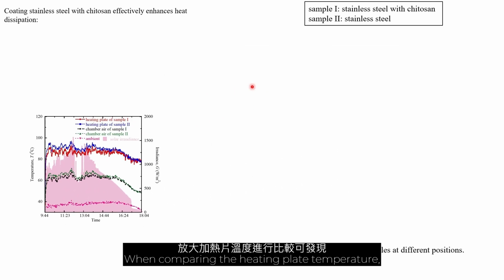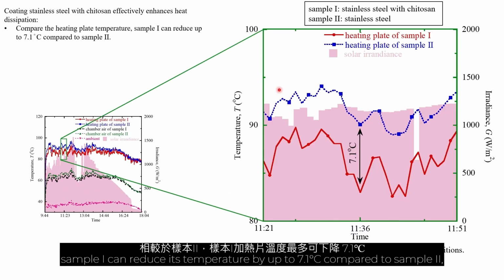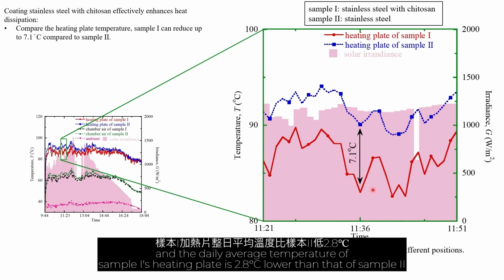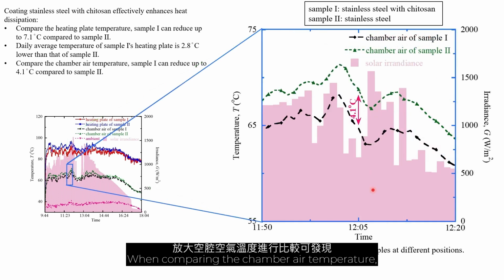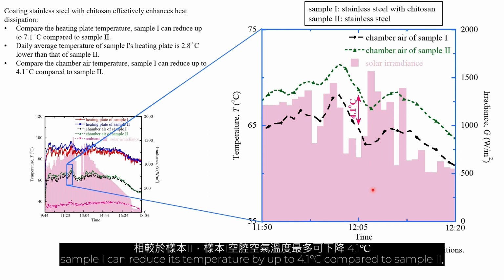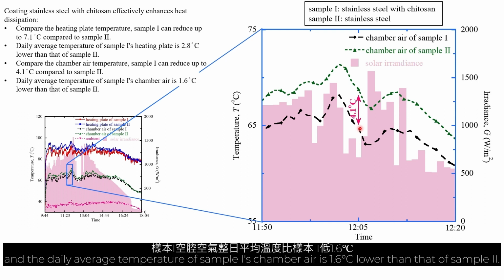When comparing the heating plate temperature, sample 1 can reduce its temperature by up to 7.1 degrees Celsius compared to sample 2. And the daily average temperature of sample 1's heating plate is 2.8 degrees Celsius lower than that of sample 2. When comparing the chamber air temperature, sample 1 can reduce its temperature by up to 4.1 degrees Celsius compared to sample 2. And the daily average temperature of sample 1's chamber air is 1.6 degrees Celsius lower than that of sample 2.